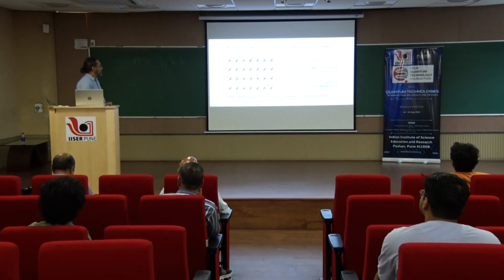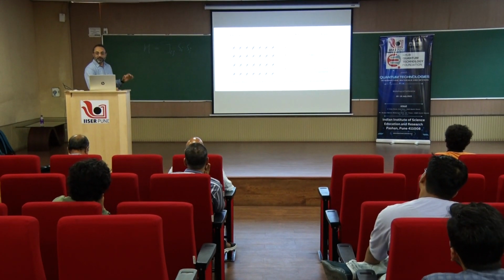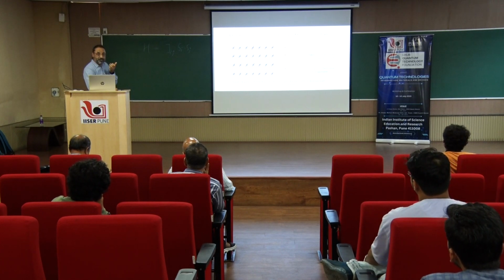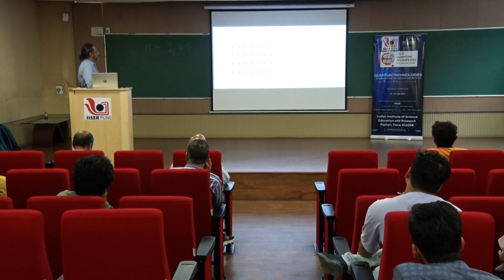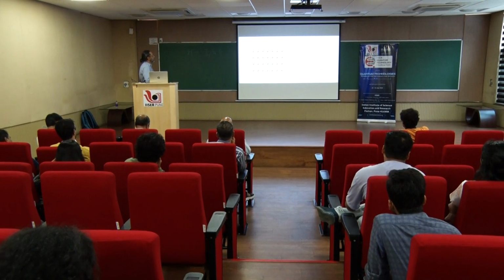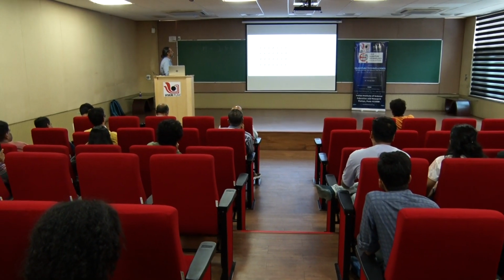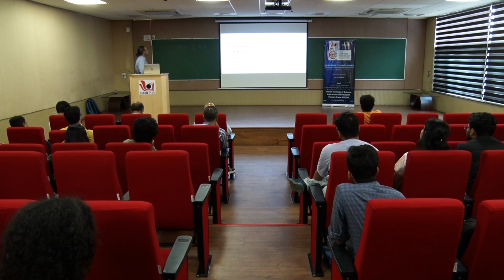And then you may ask, what is the ground state of an antiferromagnetic spin 1/2 chain? If it is not up, down, up, down, up, down, then what is it? And the answer to this is that there will be spontaneous spin flips. So for instance, this is a section of the chain. There will be a spontaneous spin flip, and once this flip has occurred, it will create these two domain wall like excitations.